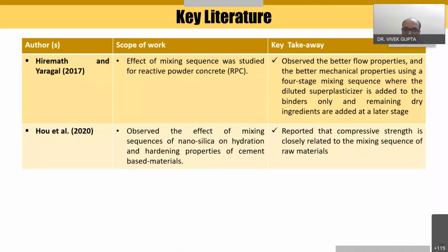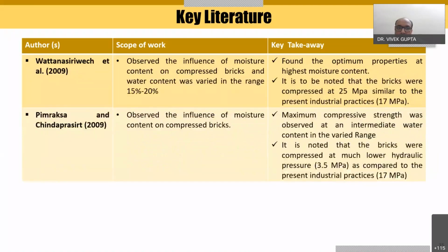Then Hou et al. in 2020 observed the effect of the mixing sequence of nano silica on hydration and hardening properties of cement-based materials, and they reported that the compressive strength is closely related to the mixing sequence of the raw materials. From there we started our work. Although we had started our work before 2020, later on we included this literature while presenting our work.